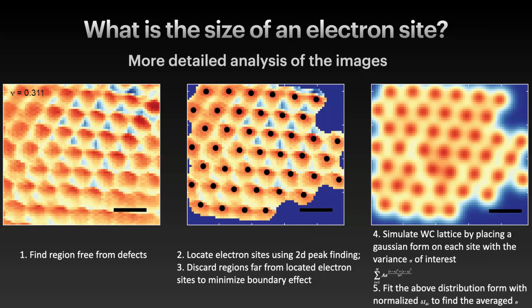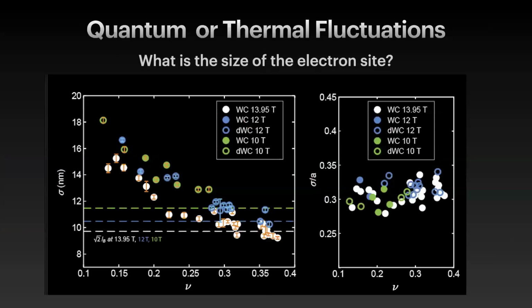You can fit this size with a Gaussian and extract a sort of root mean squared spatial size, and measure it as a function of the density of the electrons, measured as a function of magnetic field, the magnetic length. You'll find that the fit to this Gaussian gives this sigma. And you can see that as you go to higher filling, there's sort of a saturation.